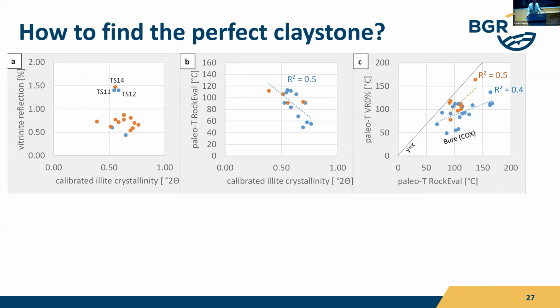On the left side, you can see there's nothing, not really any relation. So this can be explained by the fact that the illite crystallinity of this sample set has a quite small range. Normally, illite crystallinity is well suited until schists, right? Then the value is really going up. And in this sample set, the illite crystallinity is in a very small range. So the plot will definitely not be good.